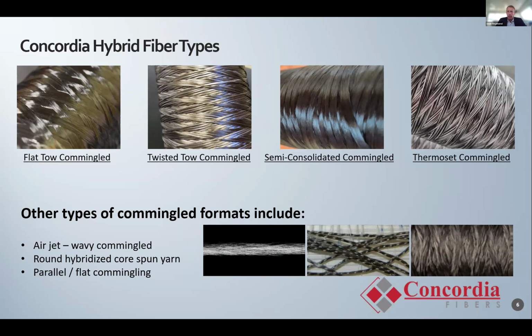And then the image on the upper right is just highlighting a commingled tow used for thermosets. In this case, we're blending a fiberglass and carbon fiber to go into tennis rackets. Now, if you compare the images above to the images below, one technology used in the industry is air jet commingling, where you're just using turbulent air and high velocity to intermingle the filaments. And what that does is it makes the fibers wavy.